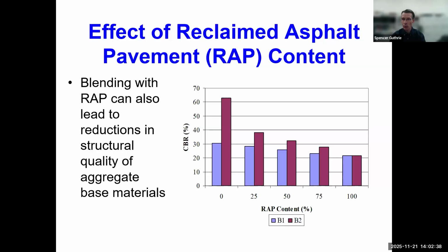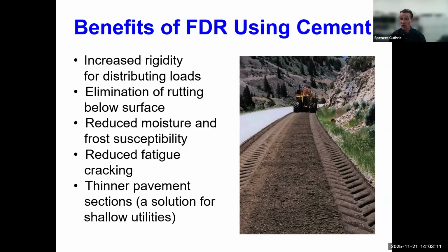Therefore, when we blend RAP with any base material having a higher CBR, such as 30 or 64 in this picture, we inevitably reduce the CBR of the combined blend. And after blending with RAP, we may decide that this blend is no longer suitable from a structural perspective, and it needs some improvement in its structural capacity. And so at that point, we like to introduce the use of some stabilization. In this case, I'm going to talk about Portland cement, perhaps the most versatile, most common kind of cement, the same cement that would be used to make concrete.